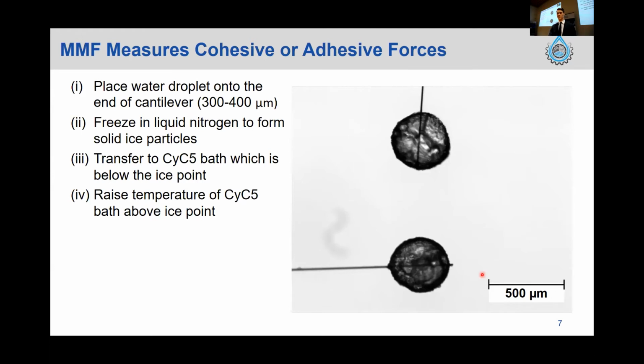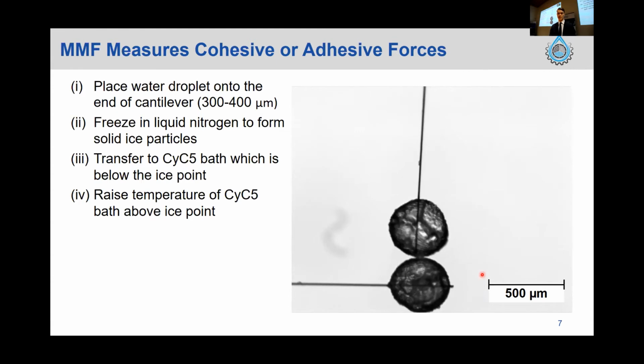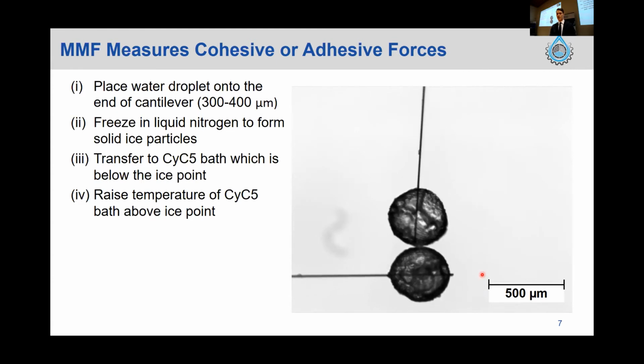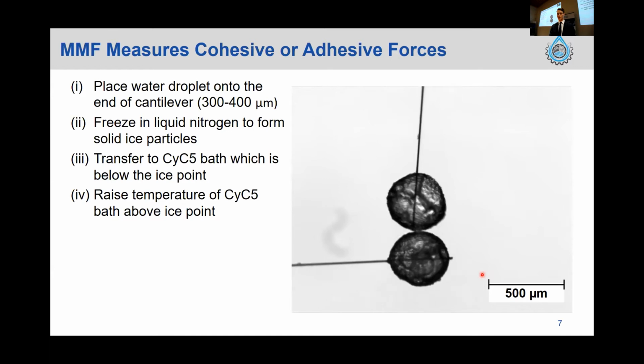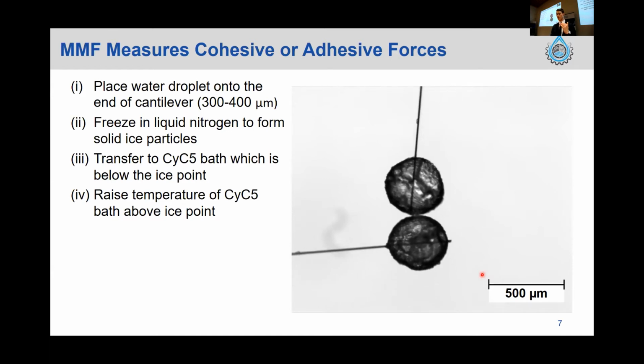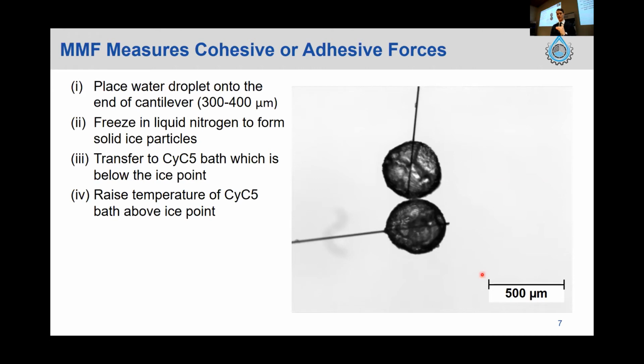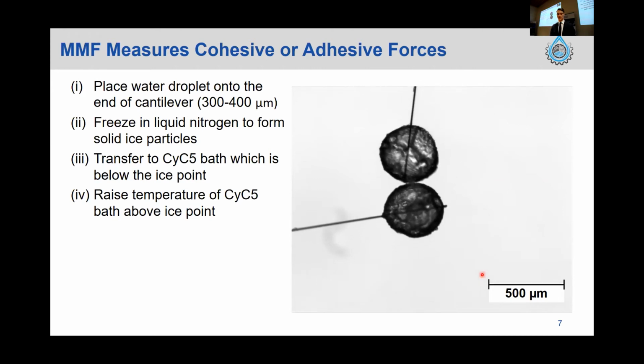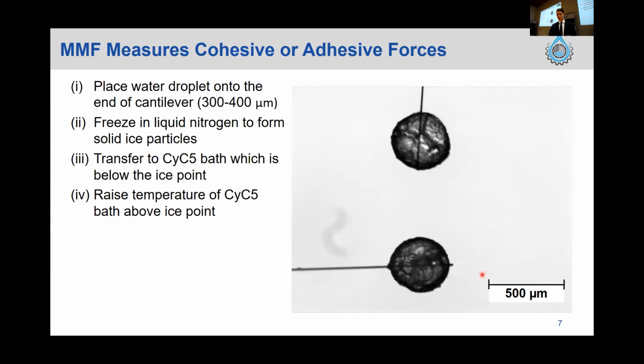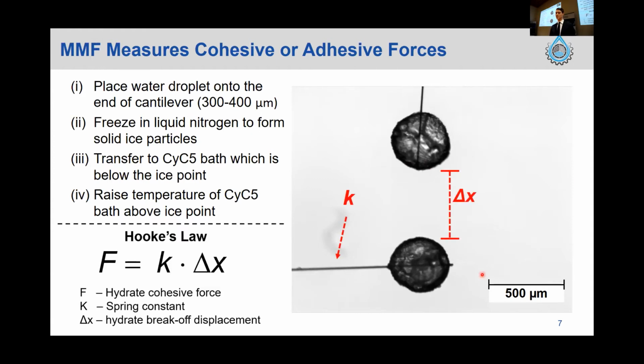So this is just a quick video of one of the pull-off trials. This is a little bit different to mine in the sense that these are 2 hydrate particles, but it gives the basic idea. So there would have been a predetermined contact time there, and now this is the actual pull-off itself. And so basically that top particle, or in my case, the substrate, is pulled off until the particle dislodges from it. There we go. And so once that happens, the displacement of the hydrate particle from the substrate, in my case, is measured, and that, along with a known spring constant of the carbon fiber, is able to calculate the adhesion force using Hooke's law.